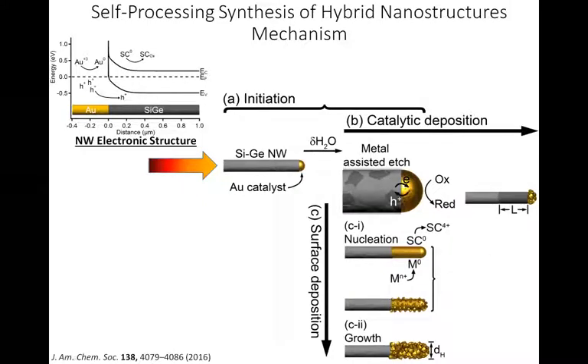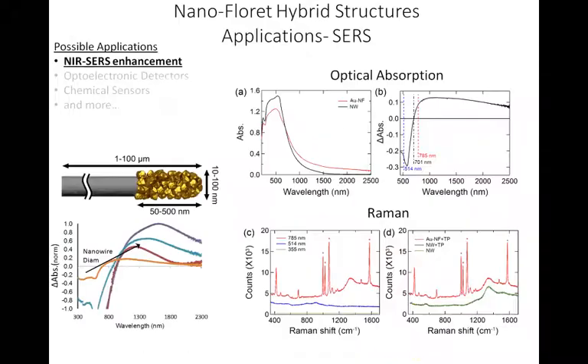We have a quite detailed understanding of the mechanism, and it works on destabilization of the oxide of the alloy next to the metal-to-semiconductor junction, and therefore we need small amounts of water as an etchant to etch the oxide of the alloy, and then by galvanic displacement and catalytic tip deposition we have the deposition of the respective metal. And knowing all these parameters, we can tune the morphologies and properties of these tip selective attachments.